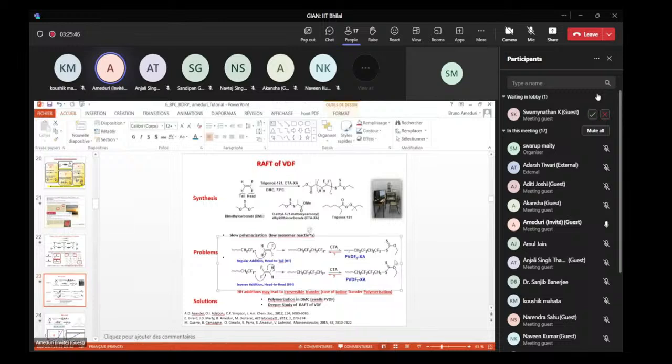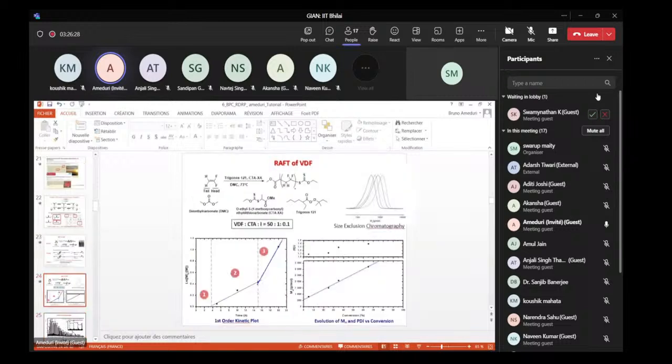So you can see that you have two different possibilities, and indeed you can anticipate, because of the electron-withdrawing effect of fluorine, that the bond dissociation energy of CF2-S will be weaker than that of CH2 xanthate. And in this case, you will have a fast equilibrium releasing radicals reacting onto VDF, but here you do not have the same efficiency, and you can have a poor reactivity with VDF. So this is important to consider, and anyway, this was the PhD of Mathieu Guerre, who did this reaction,